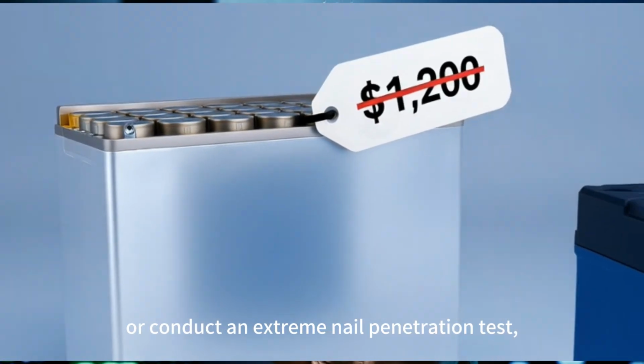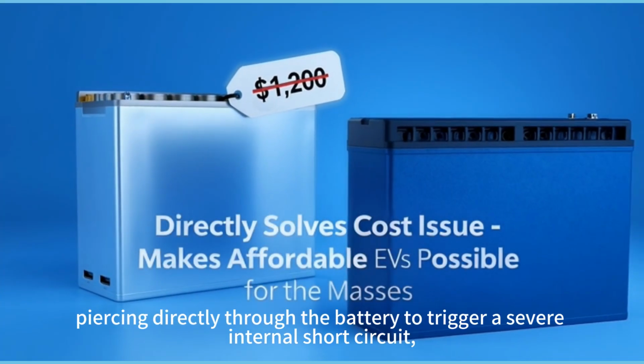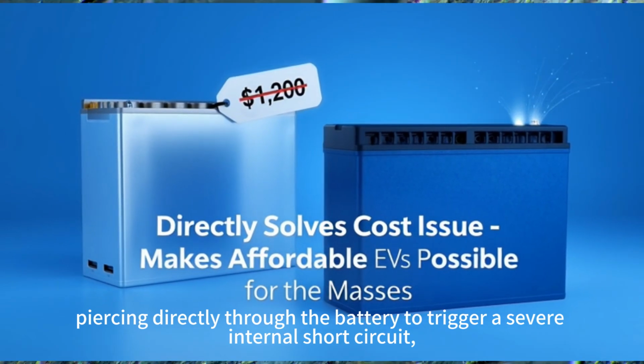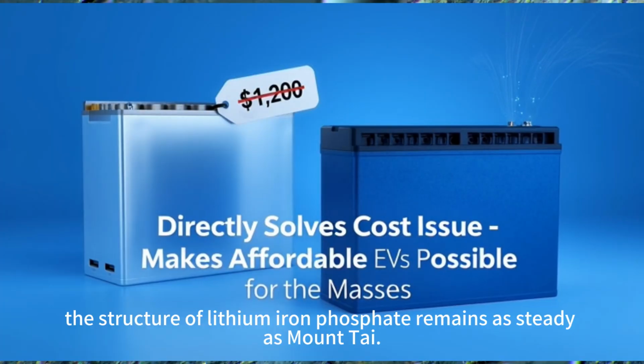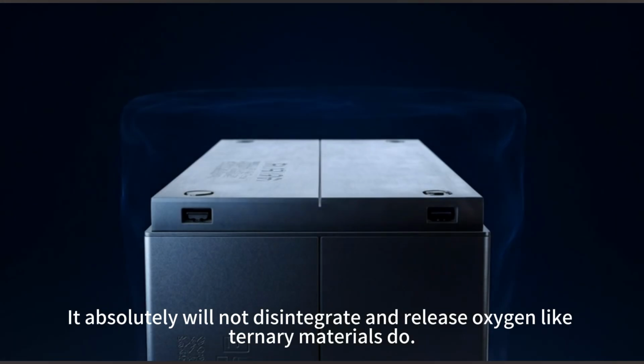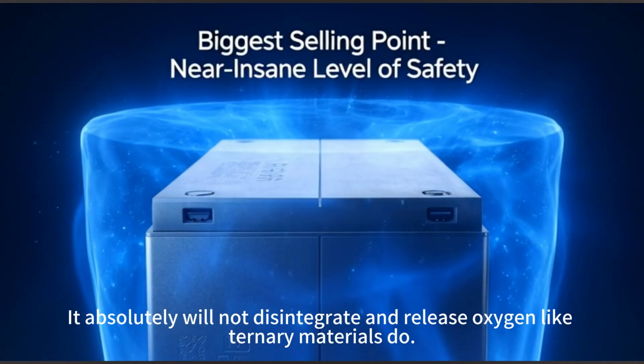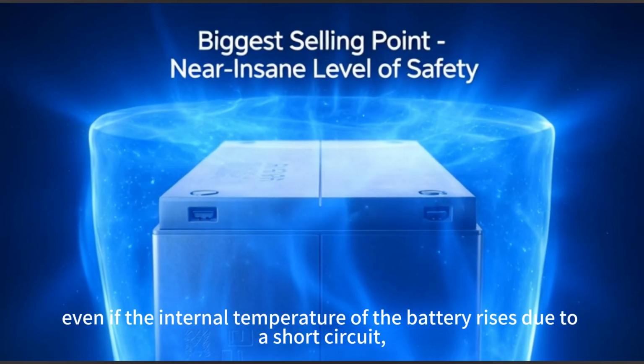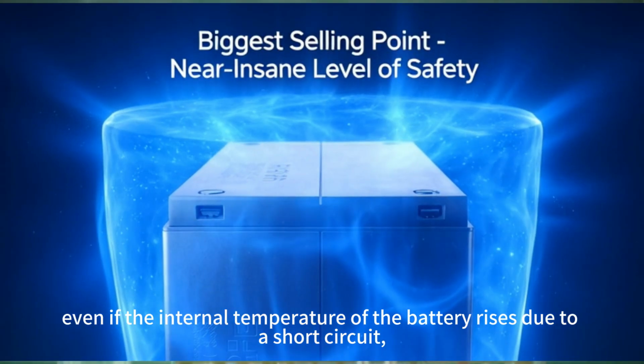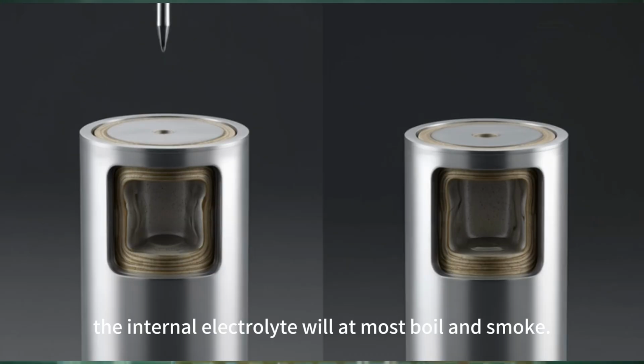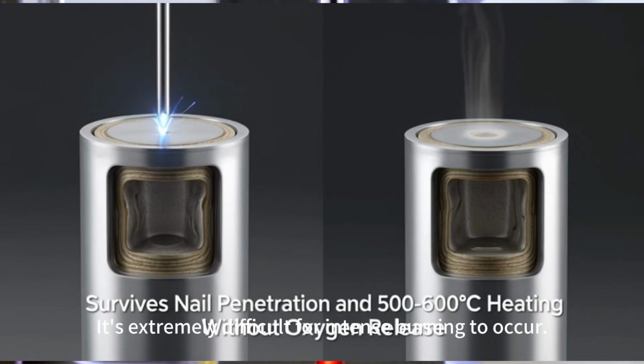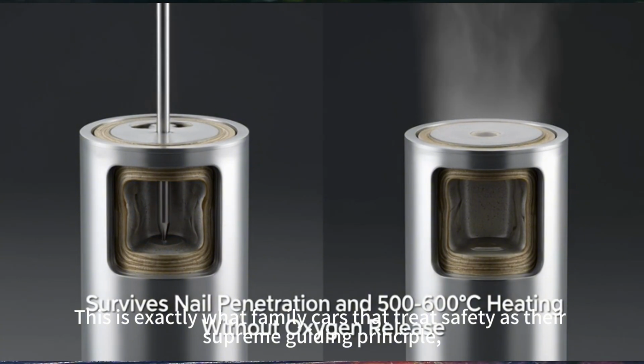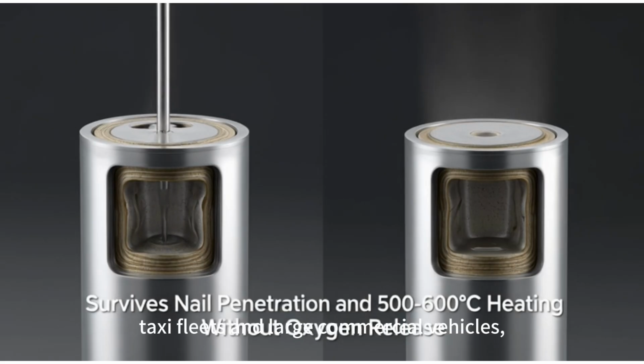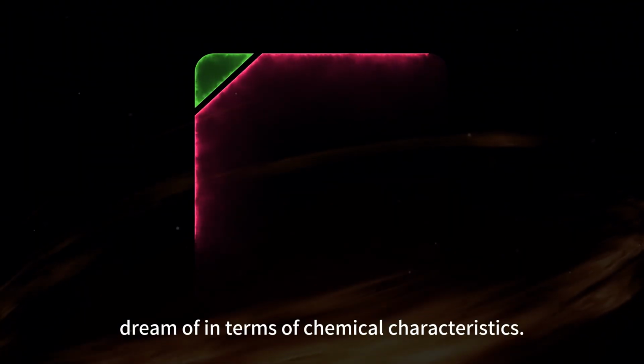Even if you heat the battery to 500 or 600 degrees Celsius, or conduct an extreme nail penetration test, piercing directly through the battery to trigger a severe internal short circuit, the structure of lithium iron phosphate remains as steady as Mount Tai. It absolutely will not disintegrate and release oxygen like ternary materials do, without the assist of oxygen. Even if the internal temperature of the battery rises due to a short circuit, the internal electrolytes will at most boil and smoke. It's extremely difficult for intense burning to occur. This is exactly what family cars that treat safety as their supreme guiding principle, along with taxi fleets and large commercial vehicles, dream of in terms of chemical characteristics.